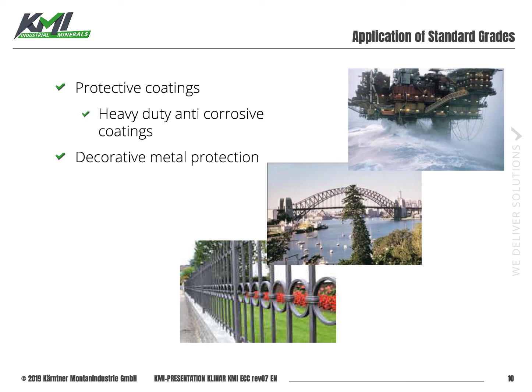When you walk around there and you look for garden fences, street lights and so on, it looks like old hammered iron, cast iron. It is a simple steel structure coated with a MIOX loaded coat with quite high loading levels. And due to these high loading levels, beside the decorative effect, you also get a protection effect.